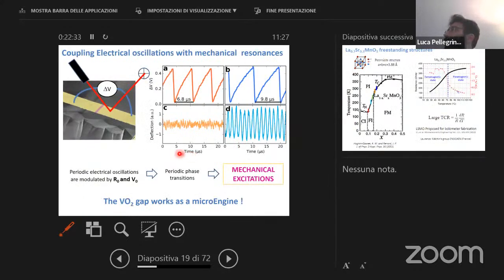And at the end, if you do measure the mechanical properties of this device, by a laser, for example, with a small power, so that you do not influence the thermal properties of this device, here is the gold pad. So you are hitting only this small region of film by Joule effect. You see that for some particular periods, your device is moving. This is because you are matching the oscillation of this voltage with the mechanical resonance of this microbridge.